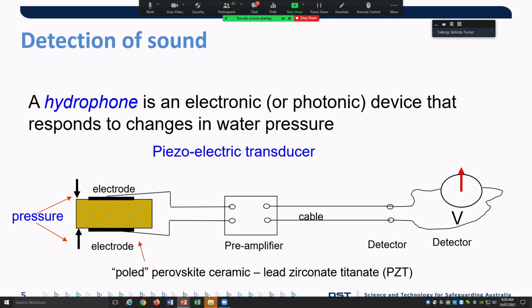Almost every hydrophone ever made for the last 60 years has been based on this one material. What's really exciting is that over the last decade or so, there are new materials, like those crystals I showed you a couple of slides ago, which have even higher piezoelectric properties—about 10 times higher than traditional PZT materials. So it's exciting to imagine the implications for the next generation of acoustic hydrophones in 10, 20, or 30 years down the track.